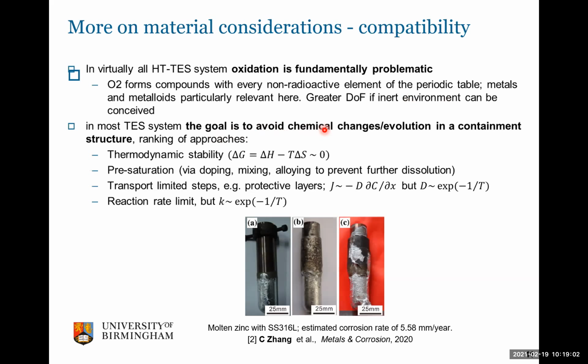So to avoid essentially degradation of the containment due to the interaction with the, let's say, molten PCM, I think there are technically four approaches. So thermodynamic stability. Here we are looking at the possibility to have a combination of PCM and containment that ultimately has a Gibbs energy of approximately 0 at the operating condition. So it's inherently thermodynamically stable, and there are a couple of examples in the literature.